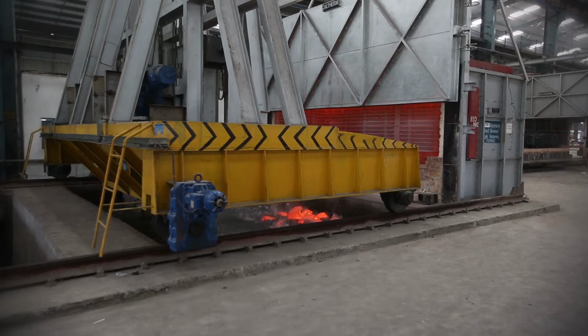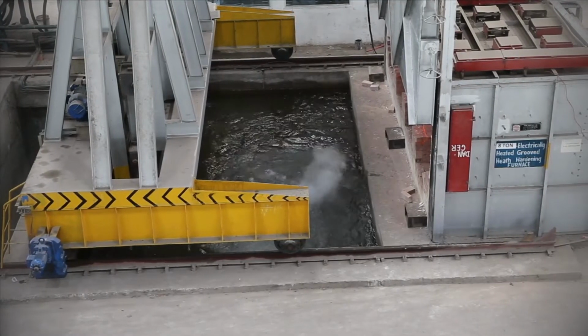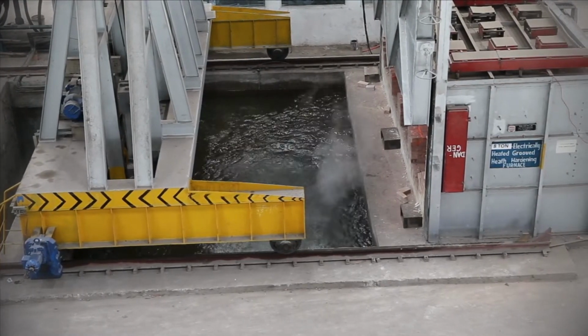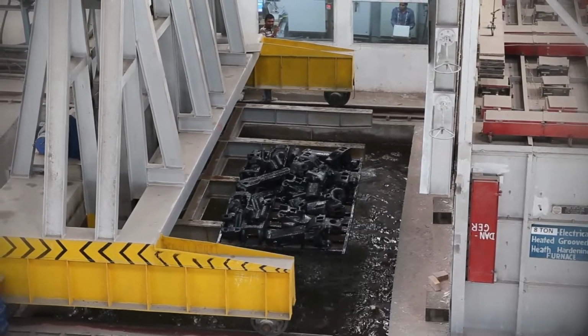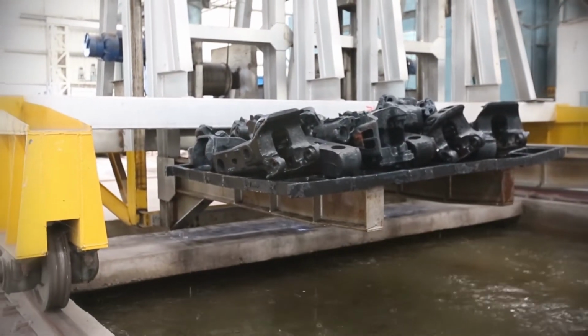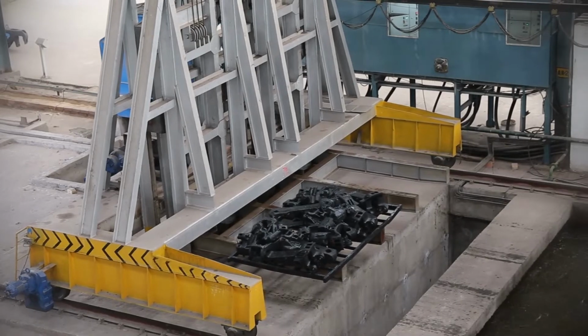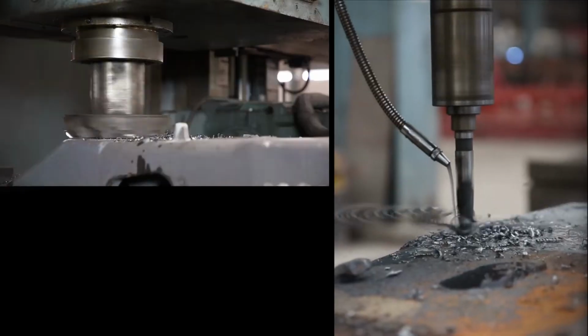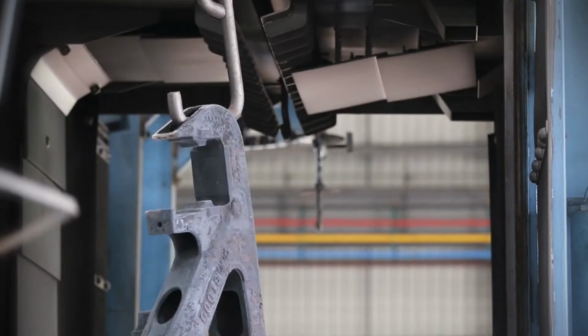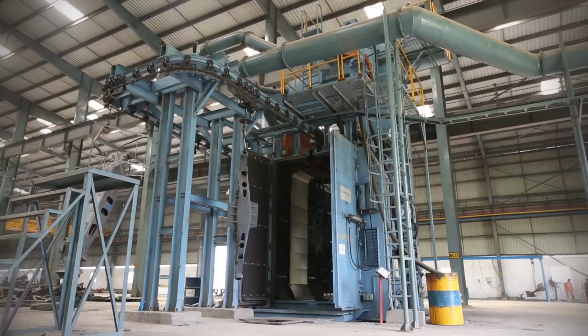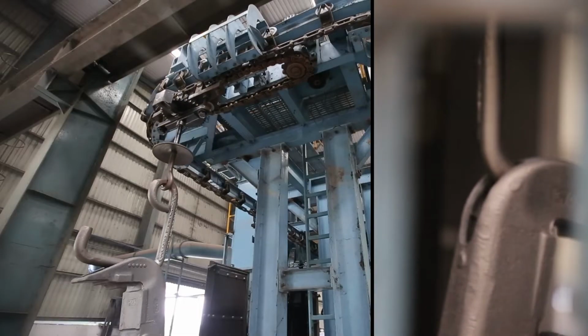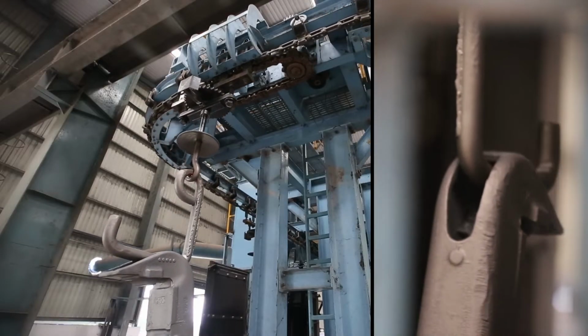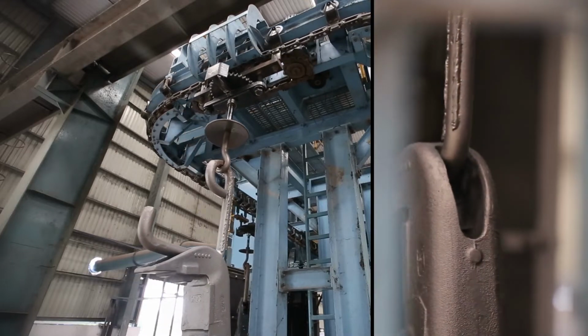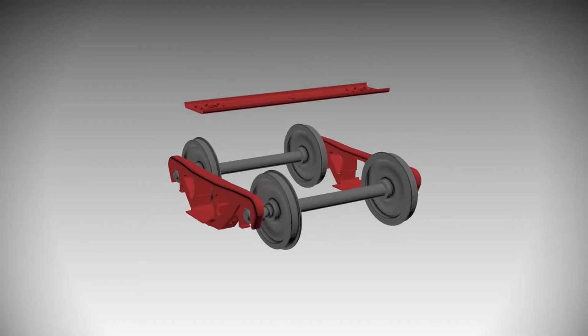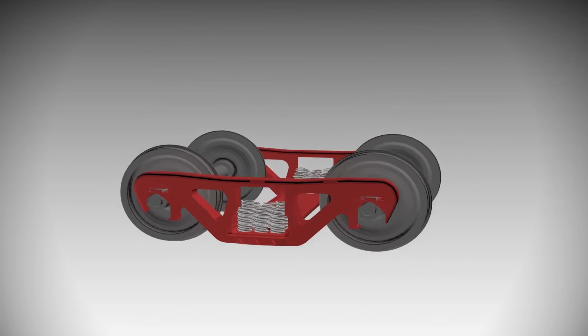Heat treatment with controlled uniform temperature leads to a better microstructure, resulting in reduced wear that lessens slack, thus improving life of the manufactured steel casting. Heat-treated castings are shot blasted before being fettled, machined and gauged. Suspended shot blasting makes the surface of the casting free from any sticking sand particles. This is done in a continuous automatic hanger-type shot blasting machine. Castings are finished and inspected as per approved gauges before assembly.